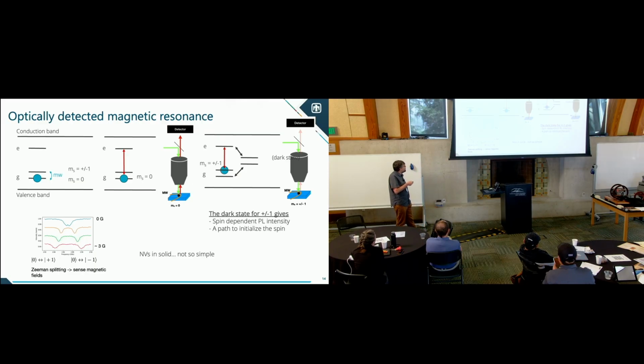And as you apply field, you can actually see that peak split into two different peaks due to the Zeeman interaction. All right, so now what have I effectively done? I can tell you what the magnetic field is, based on the amount of light coming out. Now, this is a pretty terrible measurement, not very accurate, but it gets the point across, right? As you apply magnetic field, you get splitting, and then you can sense magnetic fields.